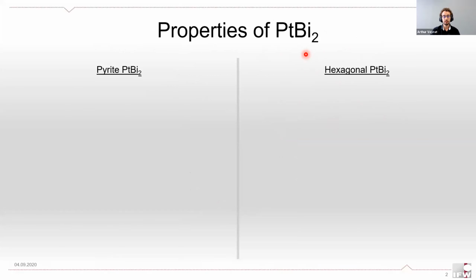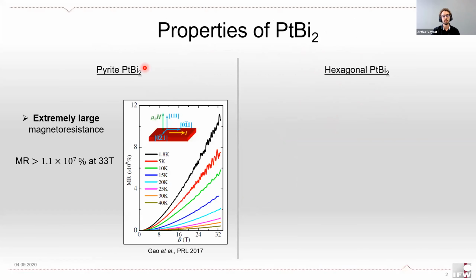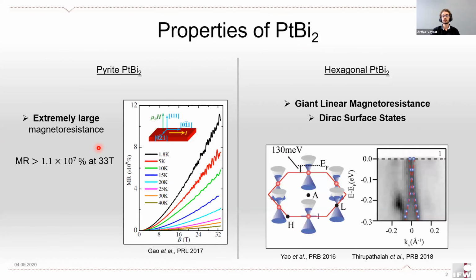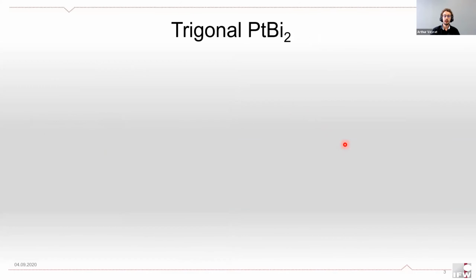So platinum bismuth 2 is a very interesting material in general. It is perhaps best known for the presence of an extremely large magnetoresistance in its pyrite structure, up to about 10 million% at 33 Tesla. The hexagonal structure also shows a giant linear magnetoresistance, which may be related to the presence of Dirac surface states at the edges of the Brillouin zone. The compound that we studied was the trigonal one.